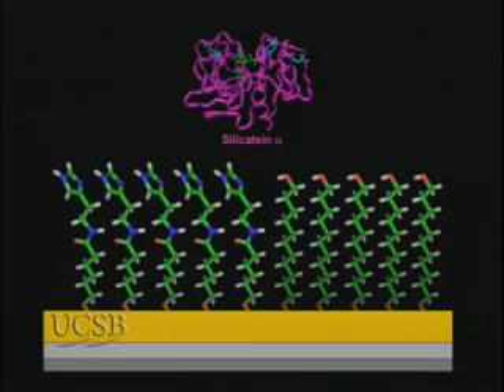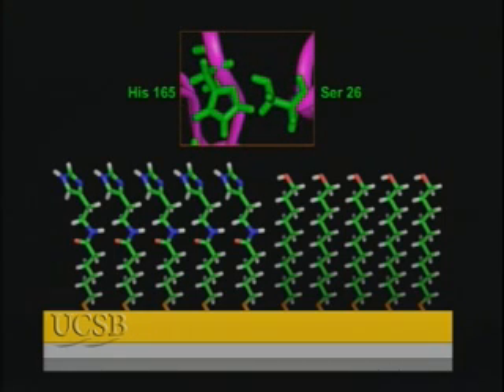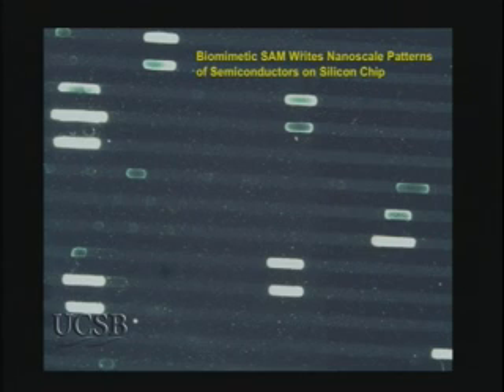Here you see the same approach, but now translated to a planar self-assembled monolayer. The protein model that we're working from is shown above. The essential groups identified as required in the natural protein are now incorporated in self-assembled monolayers with the two different functionalities on the left and the right. These results again showed that it is the interface between them that's required for catalysis and helped us confirm the notion that it is the hydroxyl groups that are the templating groups. Thus, using this approach, we were able to use the self-assembled synthetic monolayers to catalytically write nanostructures of semiconductors on a silicon wafer.